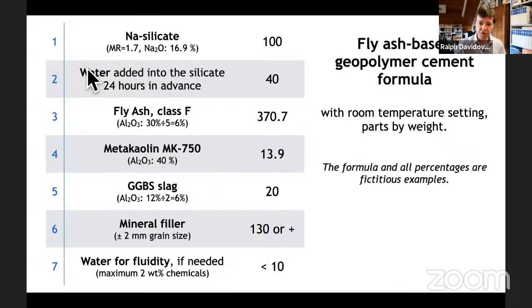So we start with the base, which is 100 grams of silicate, and then we add water, and we start to calculate how much aluminosilicates we need to add. For fly ash, for example, we have here 30% of Al2O3, but we don't calculate 30%, we only use 6%. I will not explain why we use 6% of Al2O3 in the calculation. It's part of the knowledge you will acquire in the book. I will talk about it later. Then we add a little bit of metakaolin, which has 40% of Al2O3, and we end up with this number. And slag, we have here 12% of Al2O3 in slag. We divide it by two because only half is reacting. Again, I will not enter into the details why it is so.